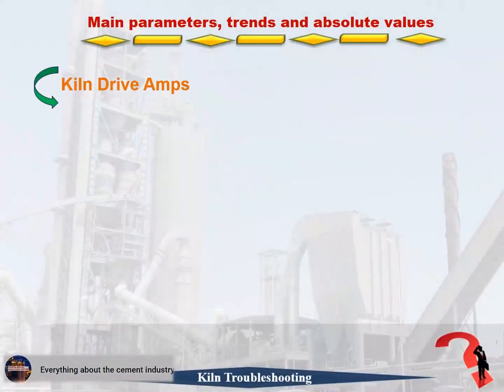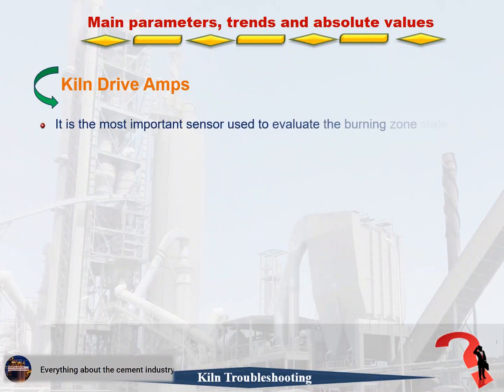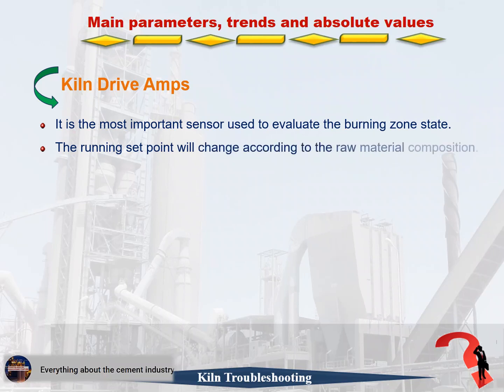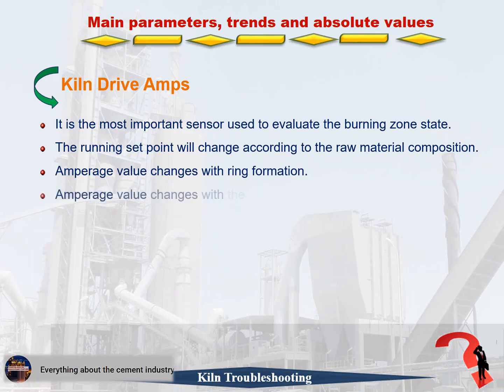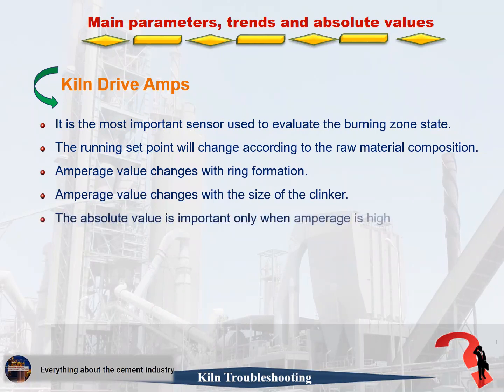Kiln drive amps. 1. It is the most important sensor used to evaluate the burning zone state. 2. The running set point will change according to the raw material composition. 3. Amperage value changes with ring formation. 4. Amperage value changes with the size of the clinker. 5. The absolute value is important only when amperage is high. Fuse protection limitations.